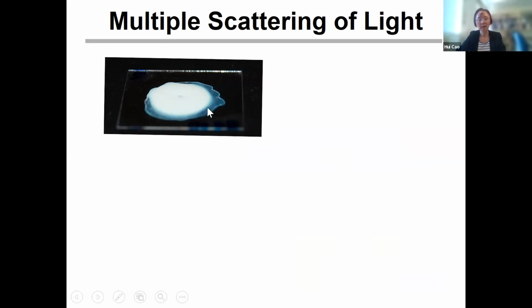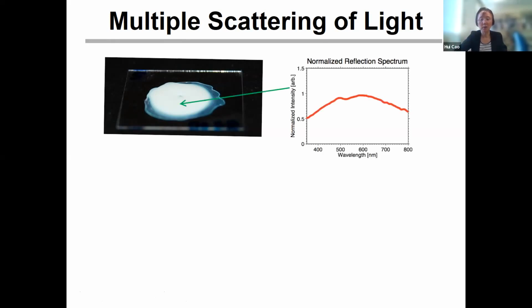So after that, we only see the blue color around the boundaries where the film is relatively thin, like in the previous case. In the center, the film is rather thick. Now we see a white color. What happens here is that if the film is very thick, then in the central part, when we see the reflection spectrum, it's pretty much a high reflection for all wavelengths. That's why you look white, because any color will be reflected.